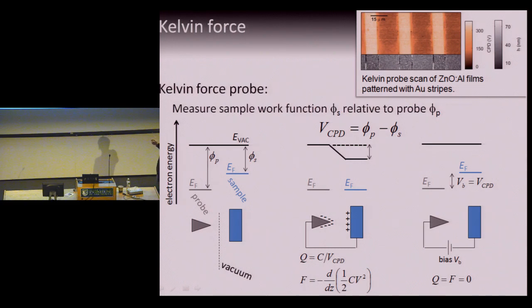All right. In practice, the way you implement this is with an atomic force microscope with a conducting tip. So you scan your conducting tip over your sample surface, you have a force transducer, and you feed that into the front end of a closed loop, and you ask the closed loop to null out the force by adjusting the bias. So this is, you know, linear control. And what you get for a real sample is a picture that looks like this. This is a picture of a sample on which I've laid down gold interdigitated electrodes. Gold has a relatively well-characterized work function. As a noble metal, it has a work function as stable as any other material you can get your hands on.